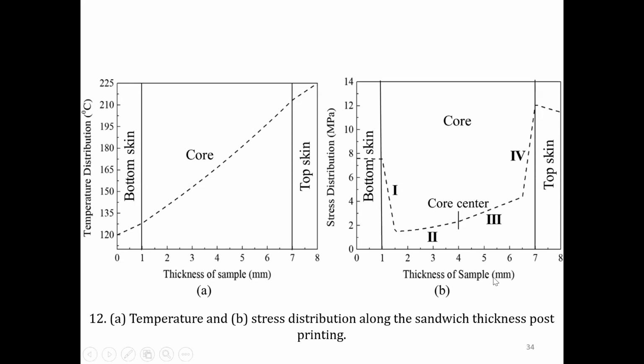So the thermal stress in the top and bottom skins is more as compared to the core due to the respective thermal properties of the skin and core, in addition to the resistance offered by the GMB particles. The stress in the bottom skin is dependent on the bed temperature because the bed is maintained constant at 120. The higher thermal stresses in the top and bottom skin as compared to the core are due to the associated temperature difference between all these systems while printing. This is basically due to the change in thermal expansion values at the skin core surface, and a sudden drop of thermal stress is observed across the interface.